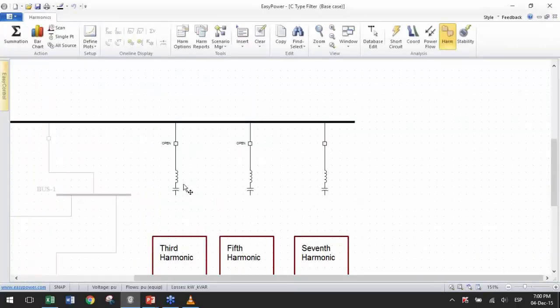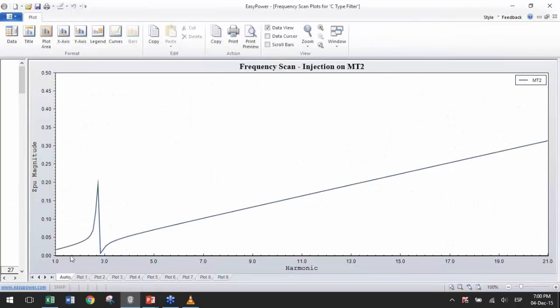Now, when I try and apply that solution to the third harmonic, let's say, I have a resonance right up in the second harmonic, which it would normally not be a problem. But as I told you before, in an electric arc furnace, I have a lot of second harmonic. And if I leave this filter here, it will produce a lot of distortion in the voltage. So a notch filter at least, more than a solution, becomes a huge problem, because of this resonance that is behind the tuned frequency.